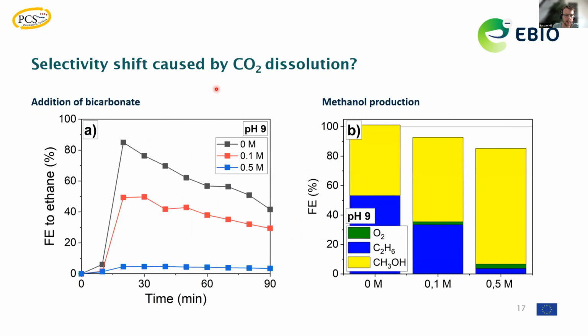So to go more into the detail, we also added bicarbonate intentionally to the electrolyte, and this is a study performed at pH 9, where we added up to 0.5 mole of sodium bicarbonate to the electrolyte. And what is quite nicely shown here by the Faradaic efficiency to ethane is that we can basically suppress immediately from the start the formation of the Kolbe product, while forming more or less selectively, shown here on the right, methanol as the Hofer-Moest product.